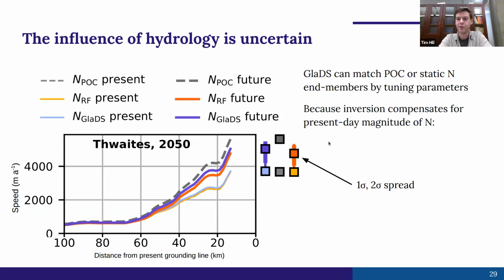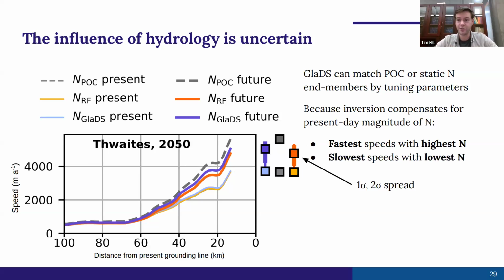There's one more complication, which is that since we have a basal friction step in between running the hydrology and dynamics model, the sensitivity to effective pressure is actually backwards. I get the fastest speed, the upper end of these intervals, from simulations that have the highest effective pressure. And simulations with the slowest speed are the ones with the lowest effective pressure. So this makes it challenging to quantify how hydrology would impact dynamics without doing the coupled modeling. And I think this random forest is a really good way to approach that, because we can take computation times from 5 days to about half a second.